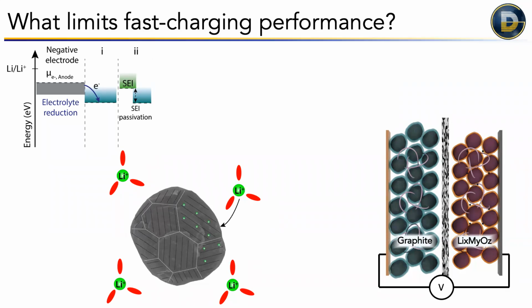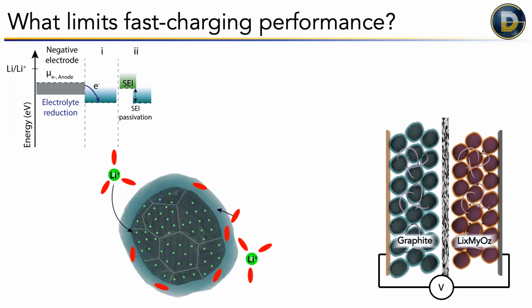But materials are not just stable at any energy level. So at a certain point, if the electrolyte has unoccupied states that electrons can go into, that will happen. So then the electrons, instead of recombining with the lithium inside the graphite, will actually reduce the electrolyte itself. It will react. So it'll consume the electrolyte and form a reaction layer on the surface. And actually, it turns out this is the only reason why lithium-ion batteries work at all.